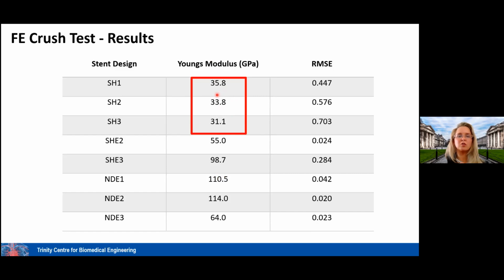And the realization here is that the reason we're calculating these to be so low is because of that dross, those particles that are attaching onto the struts in the as-print state that are essentially overestimating the thickness of the struts, but that's not really load-bearing material. So with that overestimation of thickness, essentially you will underestimate the Young's modulus. And this is again just reaffirming the real importance of etching the stents to get a better surface finish, but also to remove non-load-bearing material, which you might think is going to take the load in that stent and which would make you think you have a thicker strut in that case. So all of these are much more representative of what the load-bearing titanium as printed is in terms of its Young's modulus.